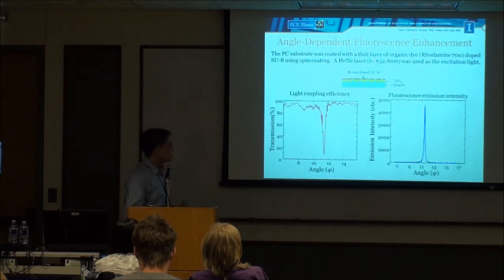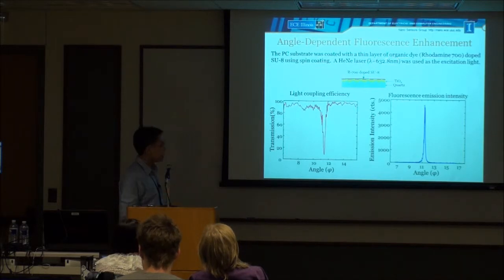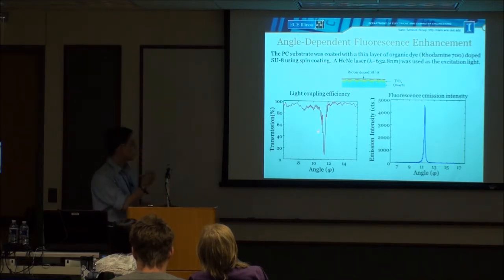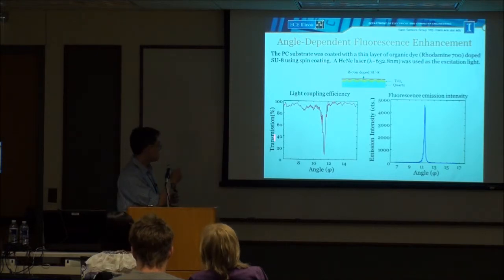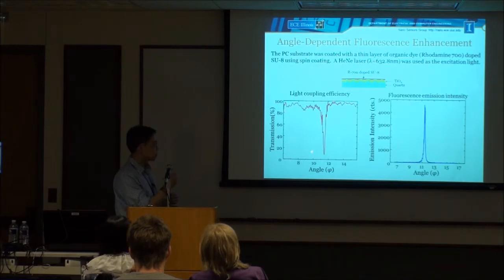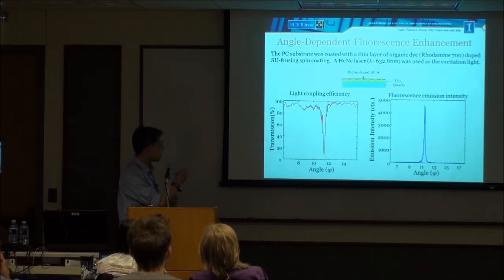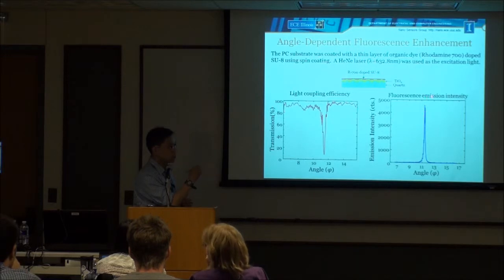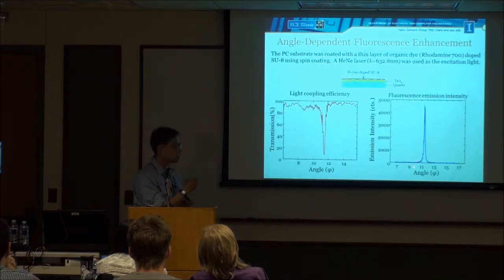So how does it look if you do a real fluorescence measurement? On top of the photonic crystal sensor, we coat a dye-doped polymer layer. The dye is Rhodamine 700, which can be excited by a HeNe laser at 633 nanometers, and it emits near 690 nanometers. When we check the coupling efficiency, we measure the transmission versus angle. If transmission is low, that means the coupling is good. When we approach the resonance angle, the transmission is less than 10%, so we got pretty good coupling. At the same time, when the light is coupled to the resonance mode, you see a very strong fluorescence signal. If you don't couple the incident light with the resonance mode of the photonic crystal substrate, the fluorescence signal is pretty low.